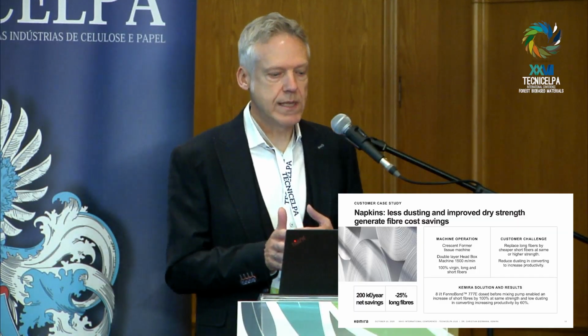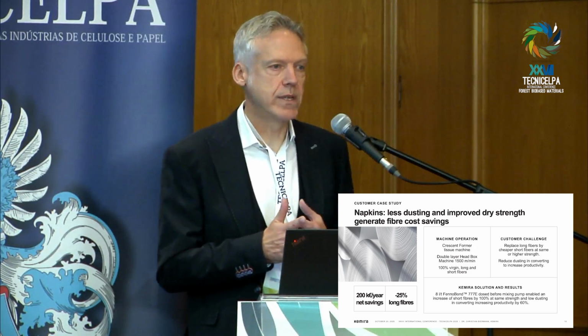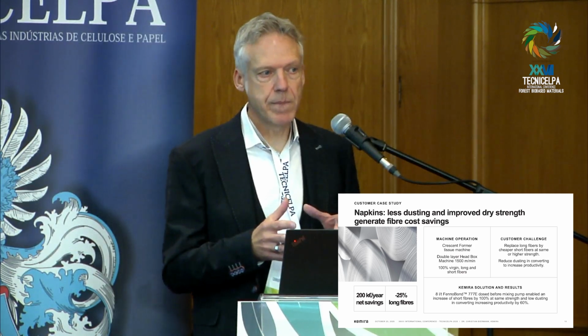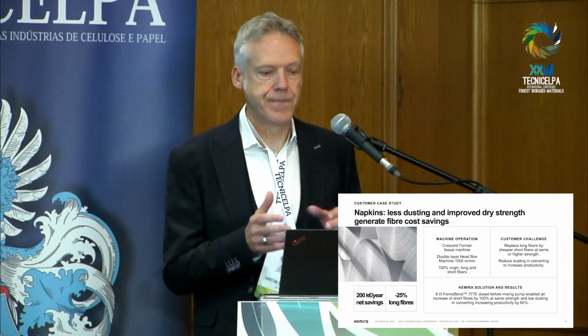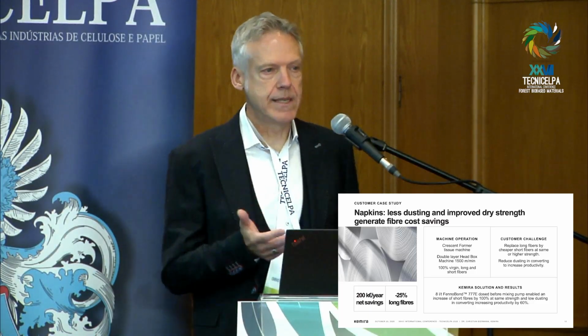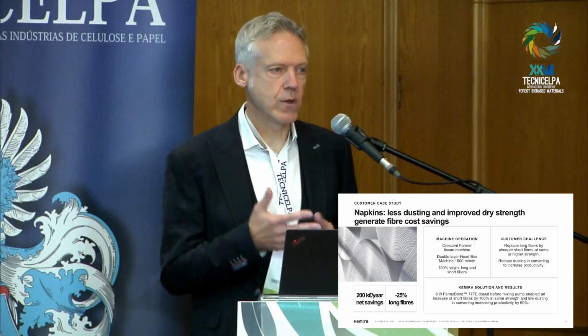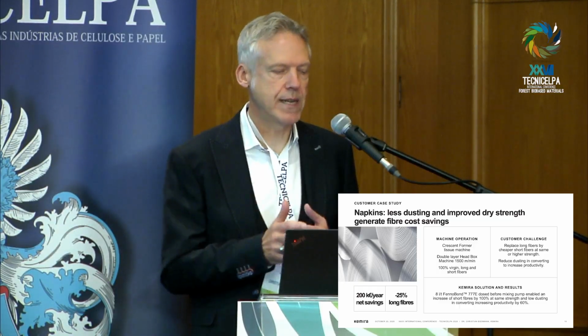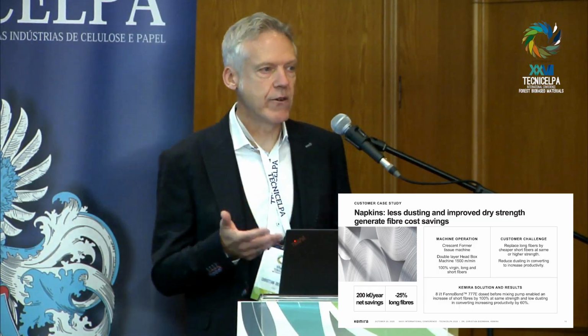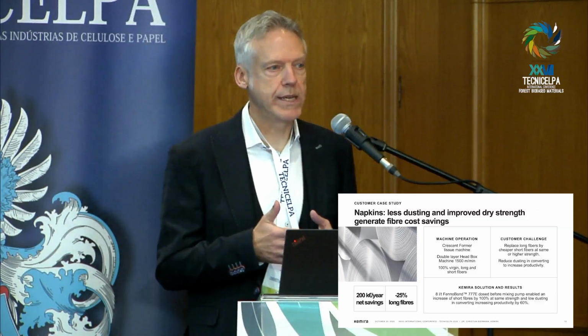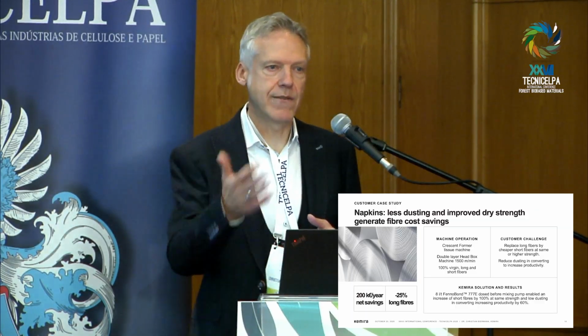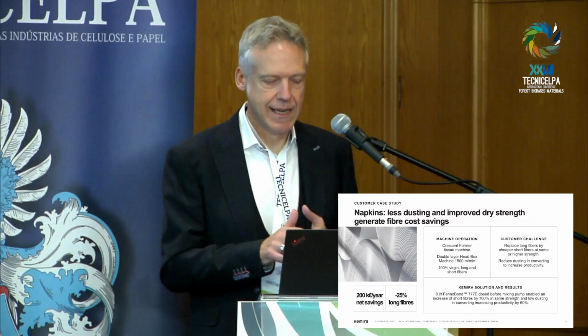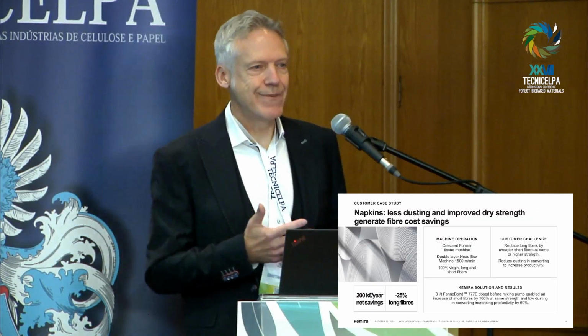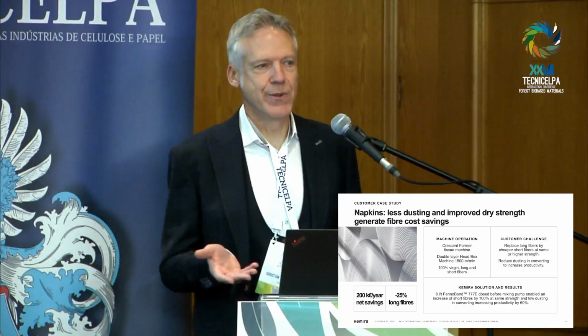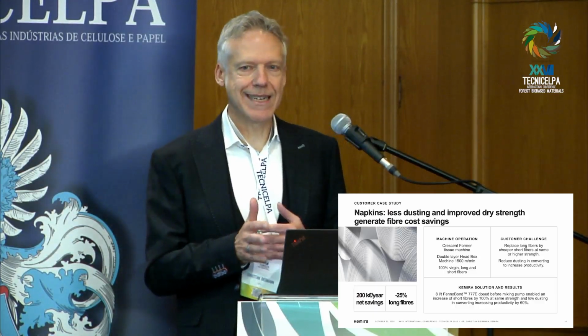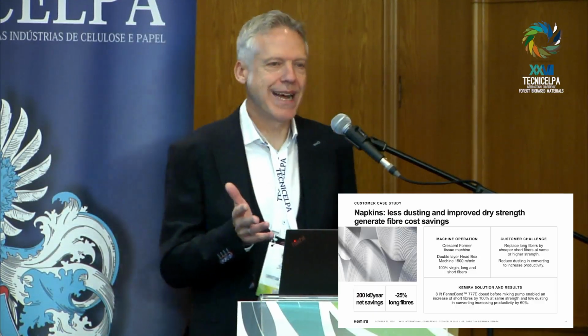At this machine, we started to dose 8 liters of FENNOBOND to the mixing pump, so right at the end of the thick stock. And that enabled them to decrease the amount of long fibers by 25%, which generates like 200 kilo euros per year of net savings. So net saving means after our product costs are subtracted. And when we got this result, we thought, okay, now we are in. Now they will start to use our product. But they were still a little bit reluctant. And we were a bit surprised, but